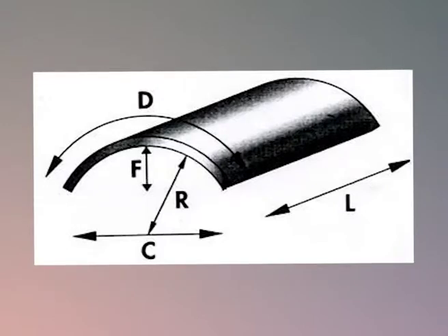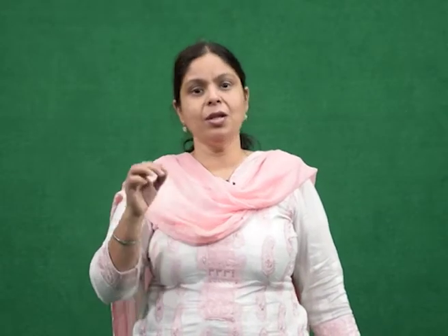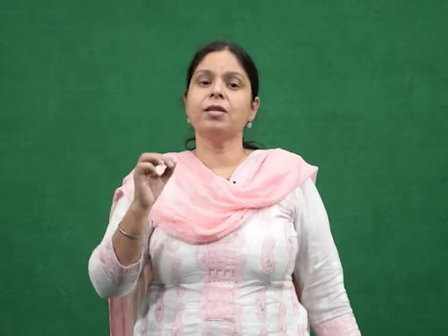Flexure and hinge stresses arise from a localized defect on the inside of the glass. A very slight impact would be enough to cause the container to fracture. This will result in a star-like appearance on the inside of the container, while at the same time causing the bending of the glass wall to the outside. The stress created by this outward bending is the hinge stress. Hinge stress fractures generally occur at the same height as the initial fracture at about 45 degrees.